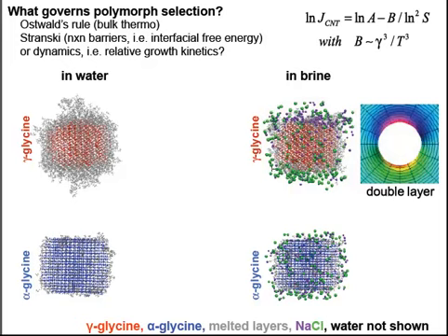free energy, gamma. Okay, now remember in the classical nucleation theory that the log of the rate is the log of a prefactor minus a barrier parameter divided by the log squared of the supersaturation. Now the barrier parameter is proportional to the interfacial free energy cubed. So if we do something that lowers that interfacial free energy, we should have a huge effect because it gets cubed and because it's inside the exponential. It should have a huge effect on that nucleation rate through this barrier parameter.